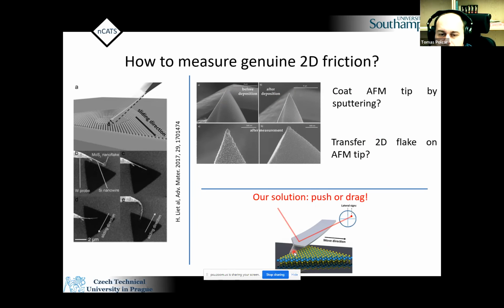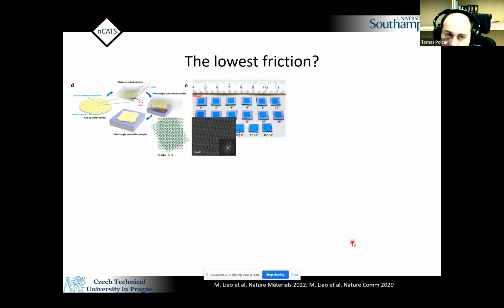So our solution was very different, and we just decided, let's use AFM, and just push the flake. Basically, you can see, we can load it here and push it, or we can drag it. We can touch it here, and because friction or adhesion between the tip and flake is probably higher than between the flake and the other material, we can drag it, and then we can load it as well. So we developed that, and we looked at what friction we can get, and it seems that we end up with one of the lowest ever measured.